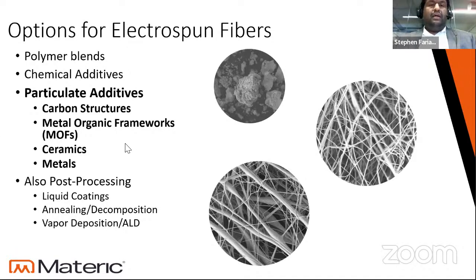So that's things like carbon structures like graphene and carbon nanotubes. We've worked with metal organic frameworks, ceramic nanoparticles, metal nanoparticles. There's a lot of different options to incorporate these additives to add that functionality on top of the nanofiber geometry and porosity that you're going to get from an electrospun material. And then there's also post-processing methods, whether that's a liquid coating, thermal treatments of your electrospun material, or even vapor coatings or atomic layer deposition. But the focus of what we'll talk about here is the things that we look out for and try to design for when we're working with solid particulate additives.